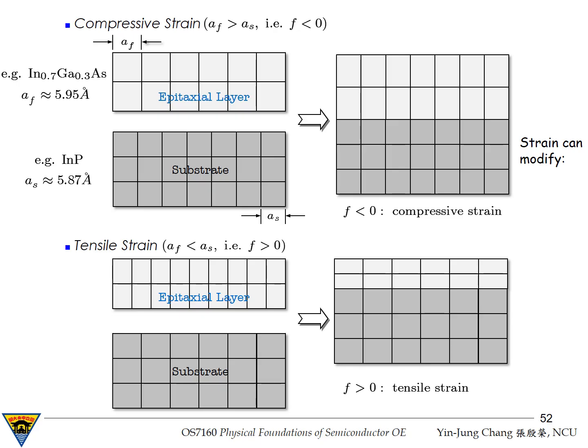Okay, so regarding tensile strain, tensile strain occurs when the natural lattice constant of the film is smaller than that of the substrate. So we have A sub f is smaller than A sub s, corresponding to a misfit parameter f larger than 0. In this case, the film atoms naturally prefer a smaller spacing than the substrate atoms. But during pseudomorphic growth, the film must match the larger lattice spacing of the substrate. As a result, the film lattice is stretched in the plane of the interface, producing tensile strain.